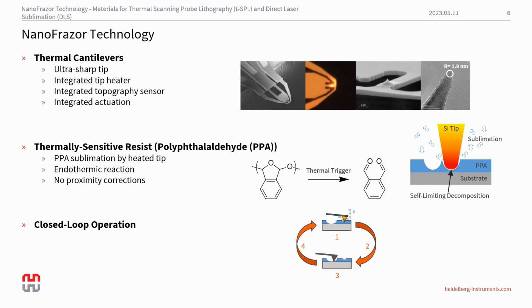So that leads to no proximity corrections with respect to the interaction of the tip with the PPA. And then finally, to close out the three main pillars of the technology is the closed loop operation. So within the software, we're able to directly pattern the topography in the forward direction, represented by the first step here. And in the second step, we are performing a retrace, or moving in the backward direction to in situ read the topography that was just written on a line-by-line basis. And so what this allows us to do is to actually see what we just patterned and correct for it based on changes to the tip or changes to the surface that we're experiencing, while maintaining a uniform pattern depth or the desired structure that we want to pattern into the PPA.